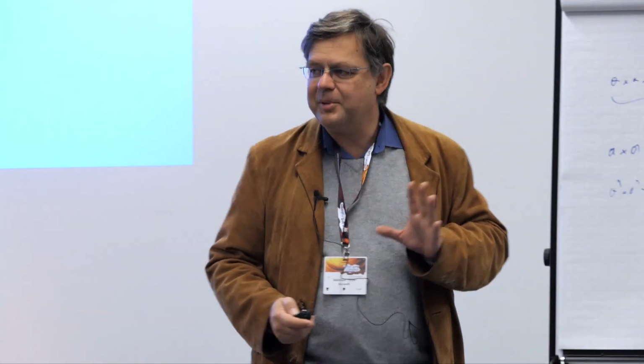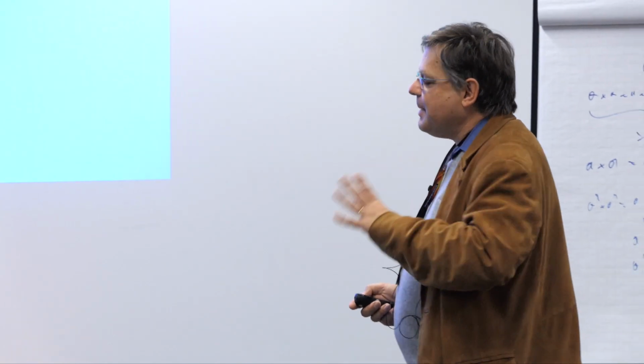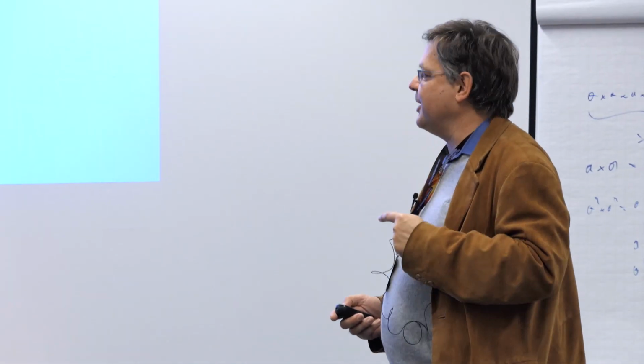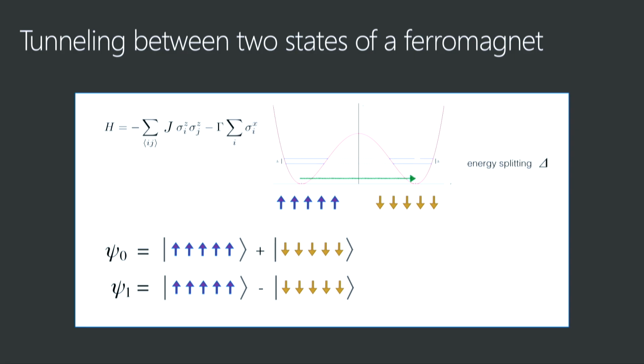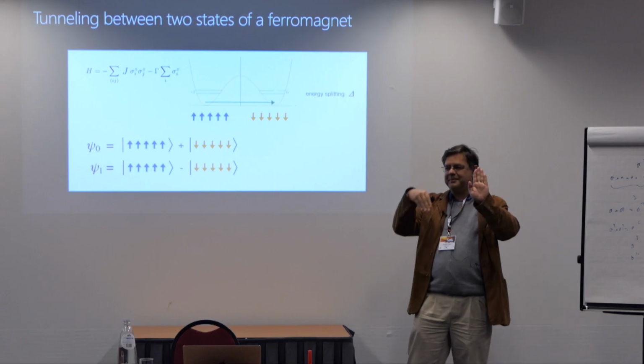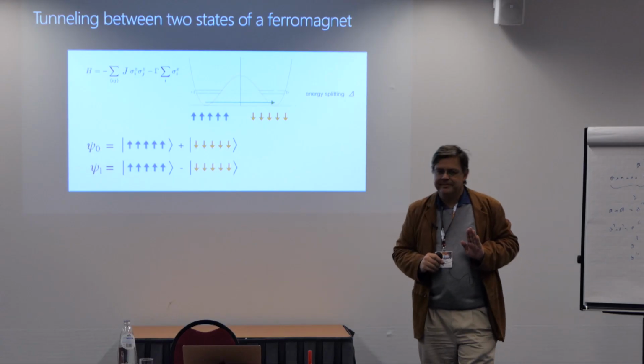And so we looked at that, for a very simple test problem. But then based on that, we could also prove some theorems. The test problem we did was just an Ising ferromagnet in a transverse field, in a weak transverse field. So the ground state will be all spins up plus all spins down. And the first excited state will be all spins up minus all spins down.